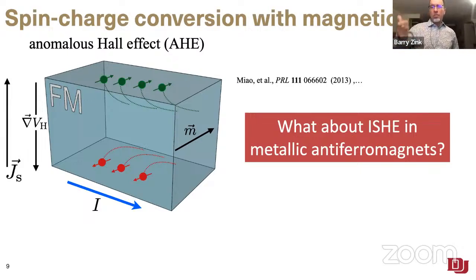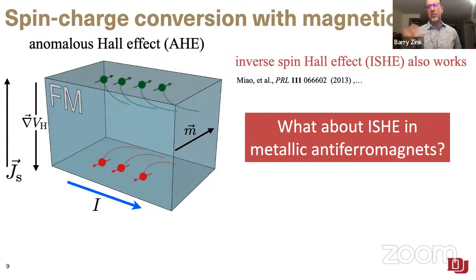So one thing that maybe wasn't really realized at that time, certainly wasn't realized until the, you know, sort of teens, is that this means that in a metallic ferromagnet, if you drive a spin current into it, it should also do the inverse spin Hall effect, right? It will also act as a detector of that spin current for you, basically. So I'm just citing one paper. There are many other ones. I should go out and dig in and expand this list so I don't offend people. But in any case, the inverse spin Hall effect in ferromagnetic metals is certainly an important thing. This sort of begs the question, as lots of us are now interested in antiferromagnets, what about the inverse spin Hall effect in metallic antiferromagnets?